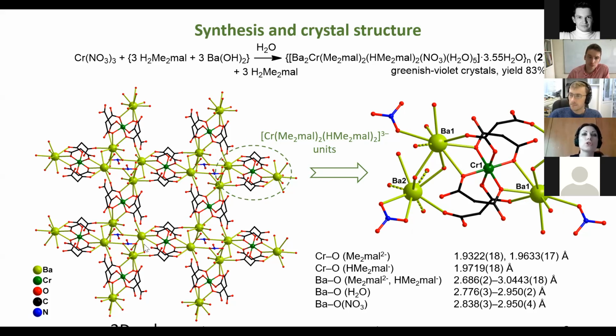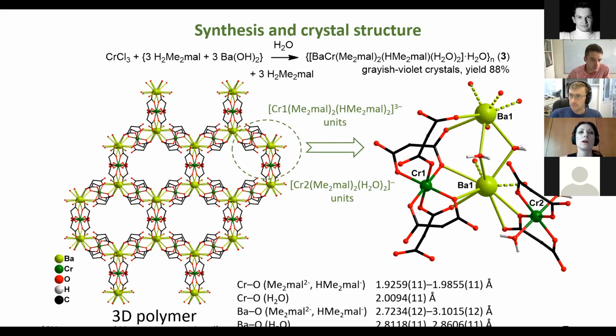The two-dimensional polymeric structure of this compound is formed through the binding of these units by barium atoms, coordinated by carboxylate oxygen atoms of the dimethyl malonate ligands. The analogous reaction, but with chromium chloride as the initial salt, afforded crystals of a new compound exhibiting a three-dimensional polymeric structure.